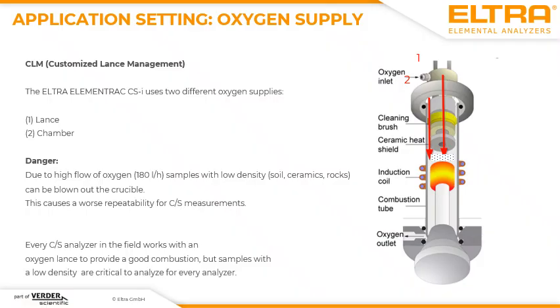And when you apply a dusty application in the ELEMENTRAC CS-i, you first apply a stream of oxygen, which is supplied by the chamber, so that you, I would say, start the combustion process. And in the middle and at the end of the combustion process, you just apply the whole oxygen via the lance. So you make sure that everything of the sample is combusted.